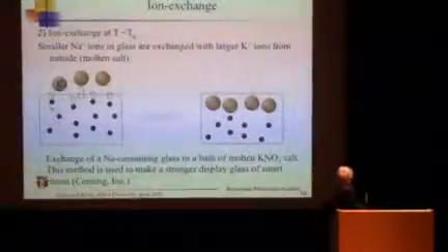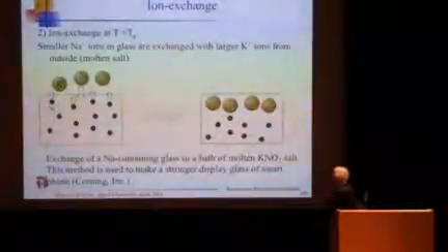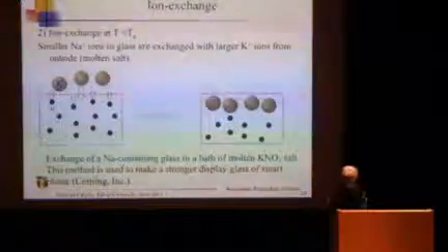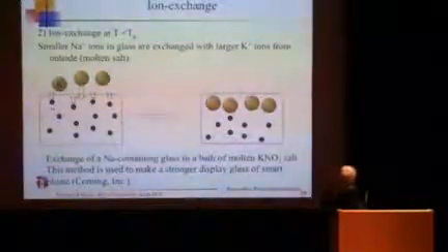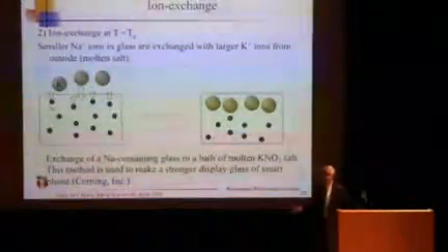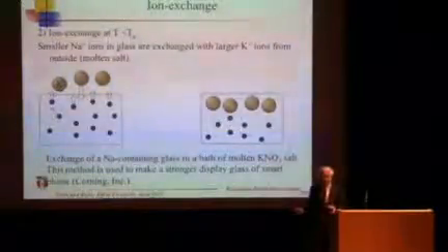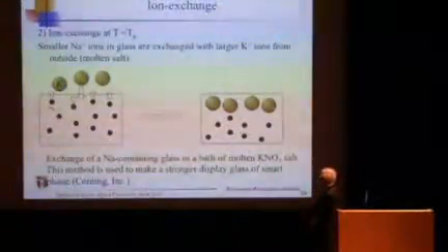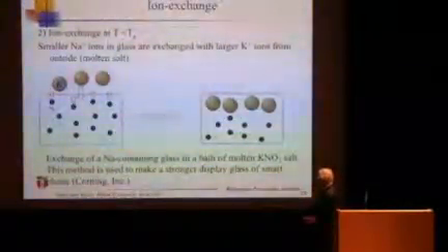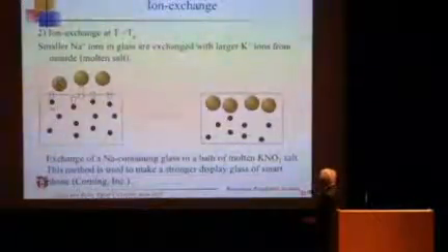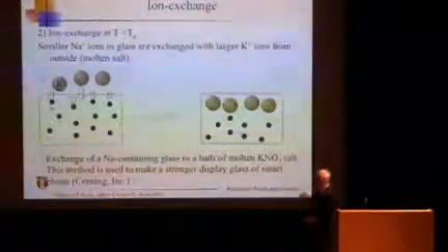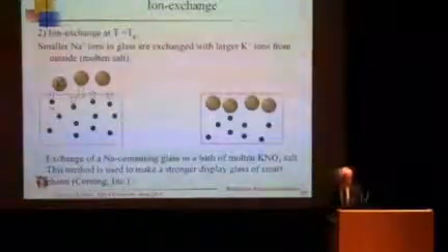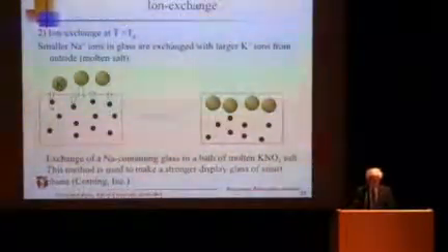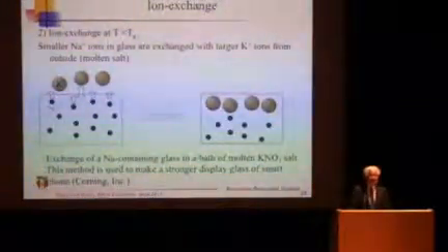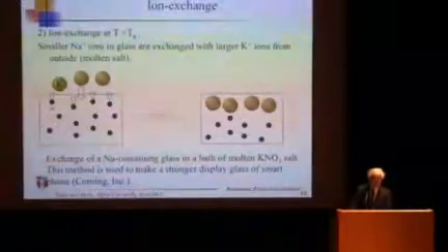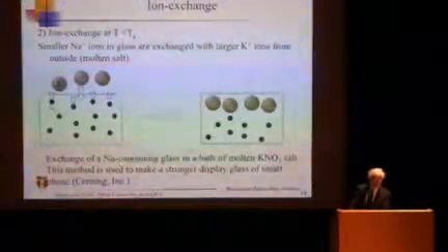The second one is by ion exchange. You take a sodium-containing glass like this, and then put it in potassium nitrate melt. The potassium is larger and replaces the sodium, and that puts in a high surface compression. That's a very effective way. As I mentioned, Corning's Gorilla Glass is made by this method. That's why your smartphone is reasonably strong.